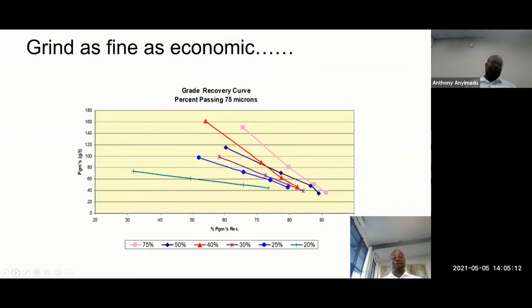So this is a flotation setup that I did quite a bit of time ago. As you can see, you start from the coarse grind, and as the grind gets finer, the grade, which is grams per ton of the platinum in that case, and the recovery go up. So what you are expecting here is that you want the curve to go into the right-hand corner. As you can see, progressively from 20, 25, 30, 40%, 50% passing 75 micron, as your grind gets finer, as expected, your recovery gets much better, which is good, no news there.